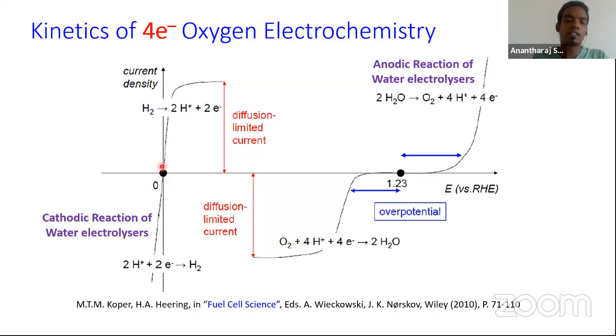In the case of hydrogen oxidation and hydrogen reduction, you can see they intersect exactly at the reversible potential where they are meant to begin. So there is no huge energy loss, literally. So the real culprit of both fuel cell and water electrolysis is the oxygen-involving anodic oxygen evolution reaction and cathodic oxygen reduction reaction. The amount of energy you lose here also contributes to the energy loss, and the amount of energy you lose here during fuel cell operation also contributes to the overall loss. So this is where we are losing energy, and this is where both fuel cell technology and water electrolysis technology become inefficient when compared to steam reforming of hydrocarbons.